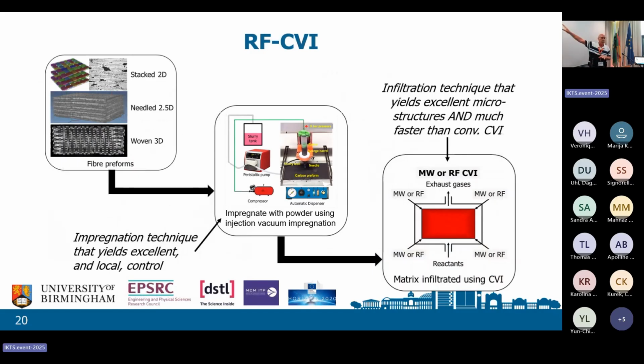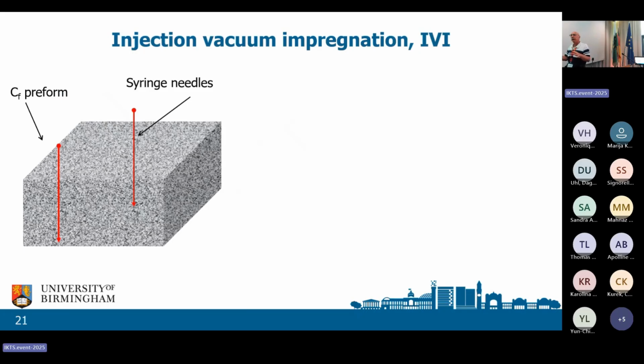So then you've got the chemical vapor infiltration. Again, you can start with whatever preforms. 2 stages. One stage is you've got to put the slurry in there, and then the second stage is your CVI. We'll go into that. So the first stage to look at is putting in the slurry. You can use vacuum infiltration, but your components will be small because you're just literally using a vacuum to suck your slurry into your preform. And if your preform is at all thick, it will go into the surface layers and no more. And you'll end up with an empty bit in the middle.